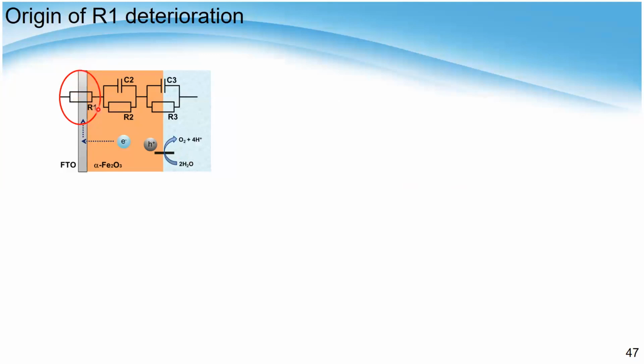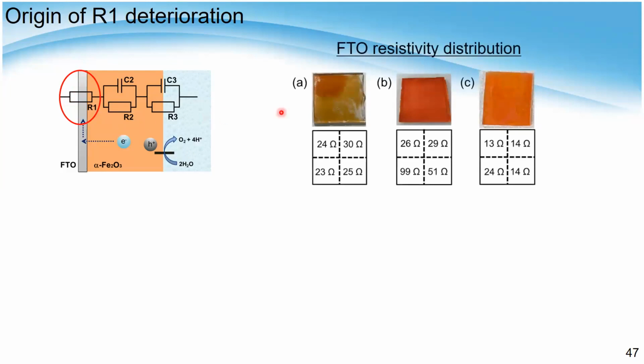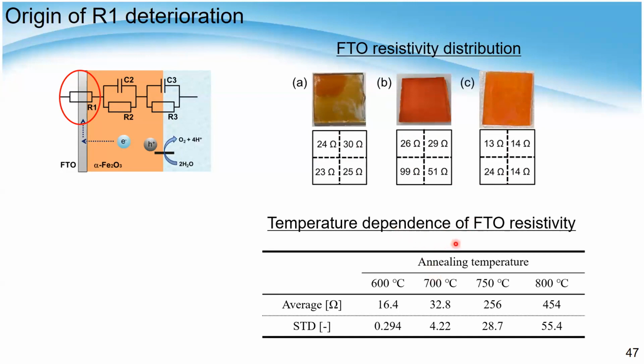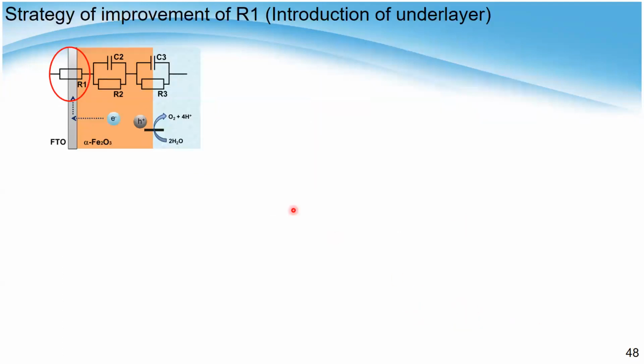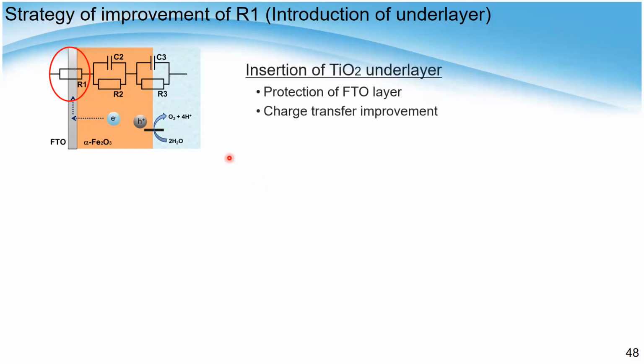So the resistance is here, at the hematite and FTO interface. We first studied the FTO resistivity for these different materials, and you could see the color difference of hematite, but the resistance itself is not much different between samples. But studying the temperature dependence of the FTO, actually FTO is degraded at higher temperature. Somewhere around here, the resistance is gradually increasing, so it is degraded. So we introduced a TiO2 layer here to protect the FTO layer. There is also research indicating that a TiO2 underlayer supports charge transport.